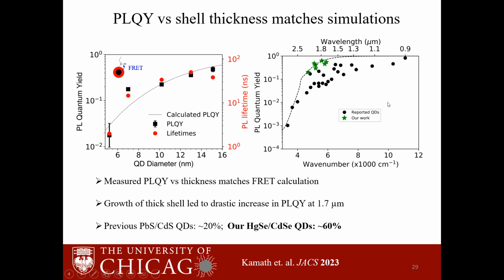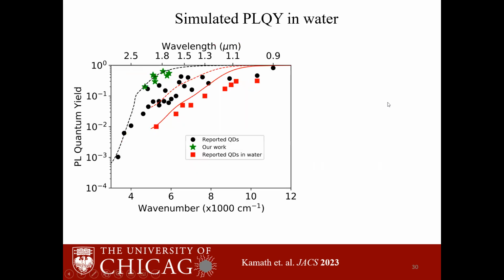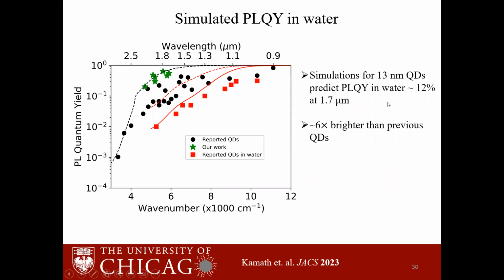And while our initial motivation was to slow the non-radiative rate for quantum dots in non-polar solvents as well as in water, we have calculated what would be the rate of non-radiative decay from the quantum dots to water molecules for our 13-nanometer quantum dots. And we see that the quantum yield is 12%. And this 12% is 6 times brighter than the previous reported quantum dots.